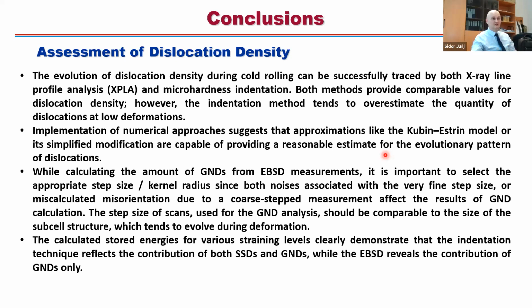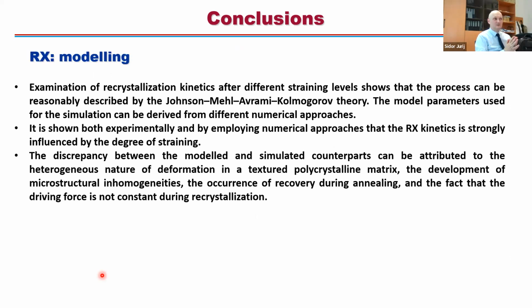And then based on these quantities, you can discriminate between statistically stored dislocations and geometrically necessary dislocations. Regarding recrystallization modeling, what we have seen is that many parameters can be derived like this. If you know dislocation density, you can calculate the stored energy, you can calculate the mobility, right? If you know the mobility, then you know the growth rate. The nucleation rate seems to be working okay now, more or less you can guess. The problem we still see is with the Avrami exponent, which seems to be a complex function of many microstructural features, right?